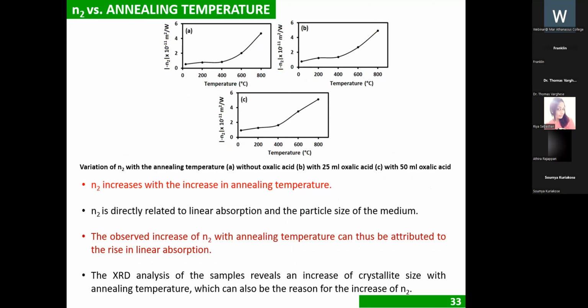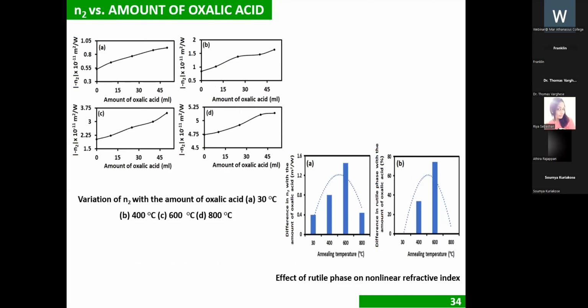That effect is here. And when we plot the amount of oxalic acid versus N2 at different annealing temperatures, from this graph and also from this bar diagram, it is visible. In the second bar diagram, the maximum change in rutile phase is observed at 400 and 600. The same thing can be observed in N2 variation also. Maximum change at 400 and 600. There is also a change at 800, but that is mainly due to the agglomeration.